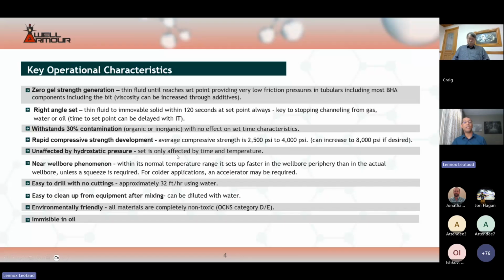With the Well Armour slurry, only temperature affects it. It is not affected by hydrostatic pressure or bottom hole pressure. Because of this, the temperature at the set point of the application, or the maximum temperature that the slurry will encounter during placement, is an important parameter. I would say both during job planning and design and during job execution, it's important to be aware of the temperature for that particular application.